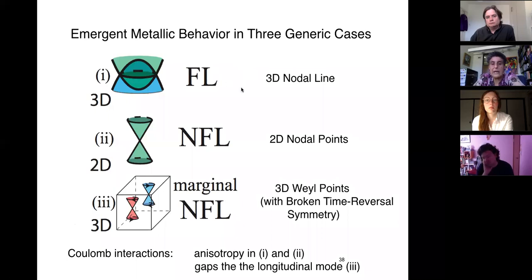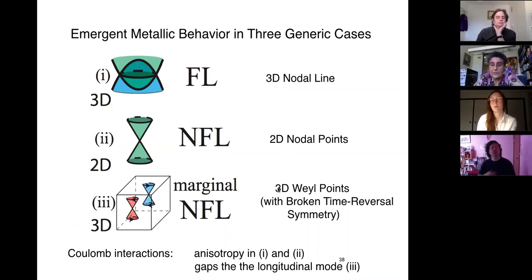Okay, so we can look at 3D nodal lines, 2D nodal points, and just for completeness, we also considered 3D Weyl points, which are driven, of course, by broken time reversal symmetry. Here we found that we had a Fermi liquid, here we had a non-Fermi liquid, and in this case, a marginal Fermi liquid.